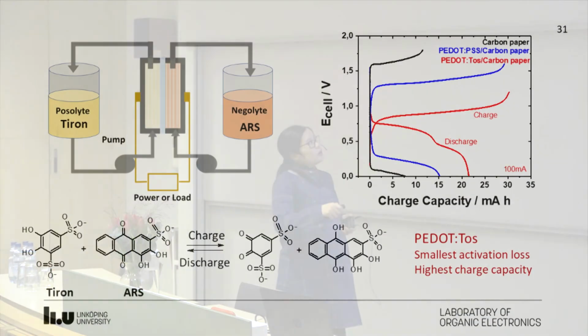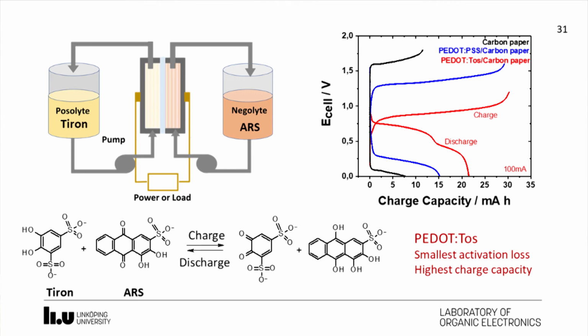This is how the device looks. Carbon paper was used as electrode material on both sides first, and we then loaded this carbon paper with P-dot PSS and P-dot TOS layers for comparison experiments. From the charge-discharge results, we can see that the cell with the P-dot TOS layer has the smallest voltage loss and also the highest charge capacity, around 22 milliampere hours, followed by the P-dot PSS cell and the least on the bare carbon cell. So from the device level, it further proves the existence of ion-selective electrocatalysis.